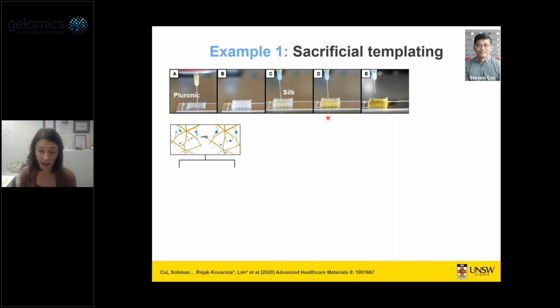That would make sense. And we can, and people do. However, in our lab we like to work with quite low concentrations of silk for soft tissue applications, fast degradation, fast remodeling. And low concentrations of silk typically do not have the appropriate viscosities necessary for that good printing window. And often in 3D printing, you have to optimize that printing window at the expense of your ideal material properties. And so for that reason, we're big fans of sacrificial templating, where you print a material that prints easily, and then you cast your material of interest on top of it.